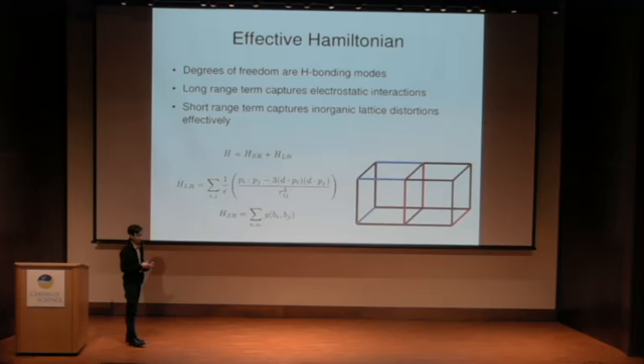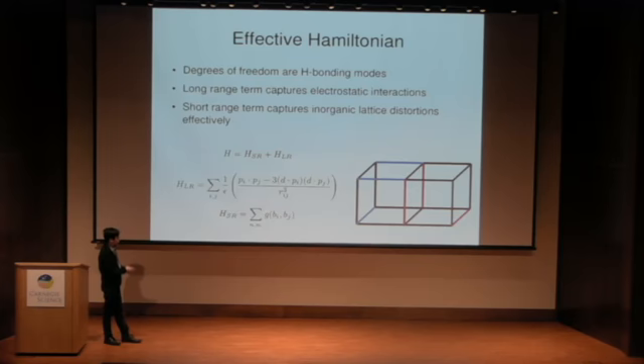And at first sight, it's tempting to use some kind of simple formulation for this short-range term, like a vector-like coupling, maybe like a dot product between the orientations of the two molecules, for example. But actually, that's not an appropriate description. I found that the better description is to use these types of bonding patterns as variables in the effective model, and introduce couplings between different types of bonding patterns. So one example is shown here. You have a red type bonding pattern with this orientation, coupled to a blue type bonding pattern with a different orientation. And for each possibility, there's a different coupling.